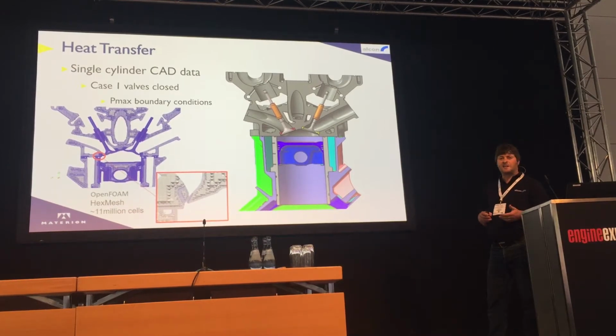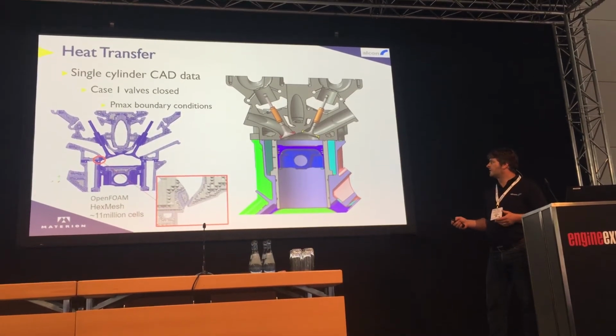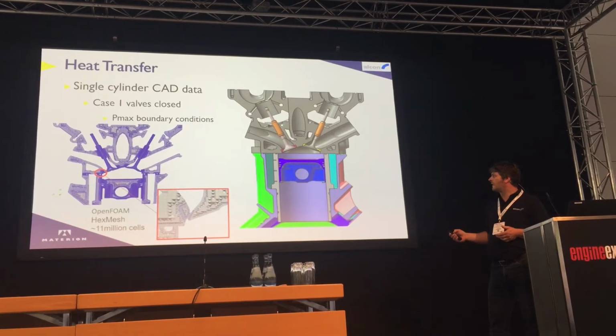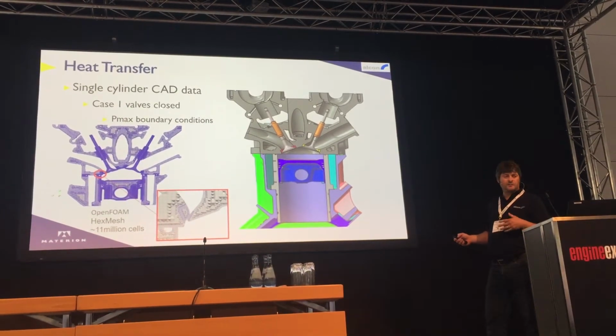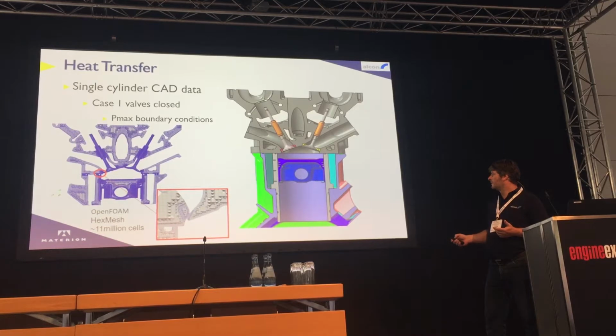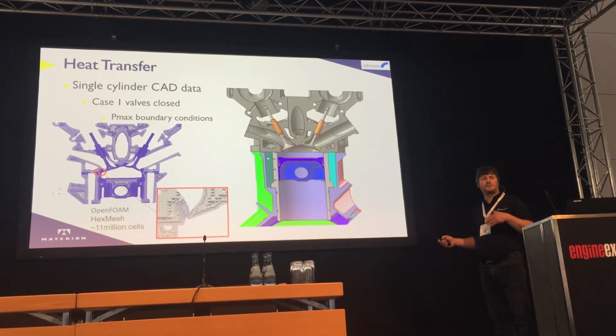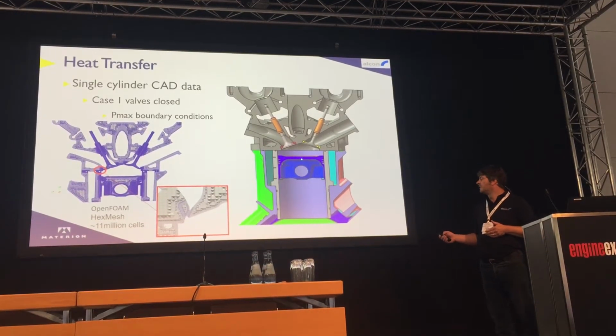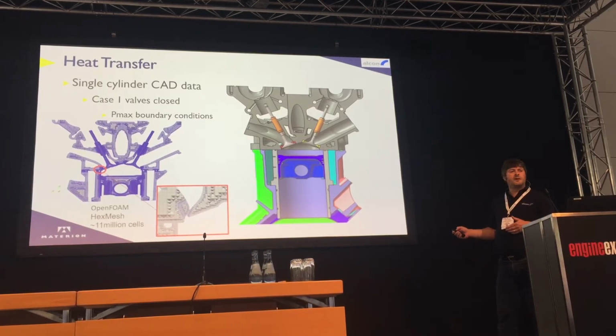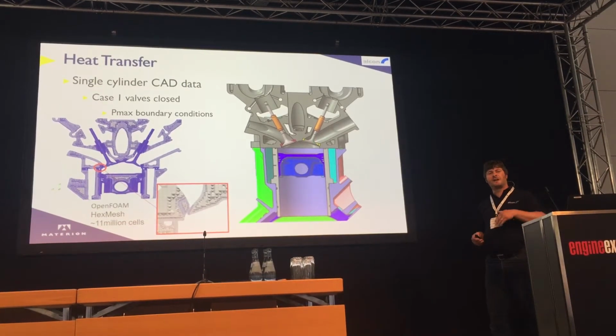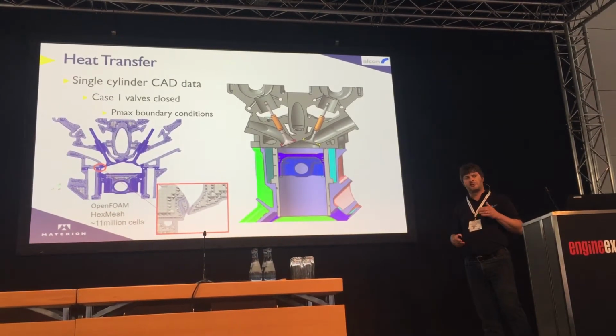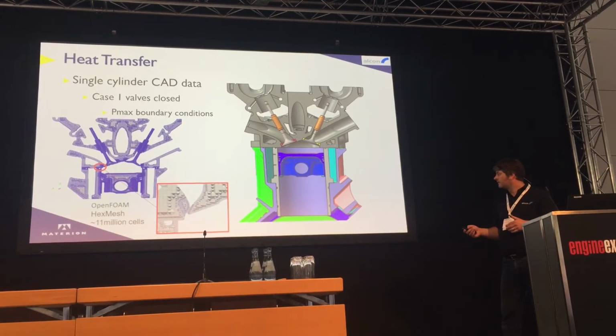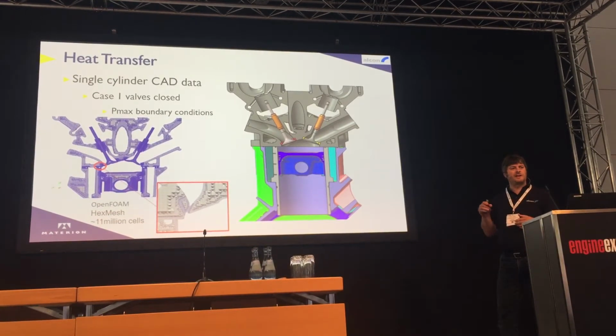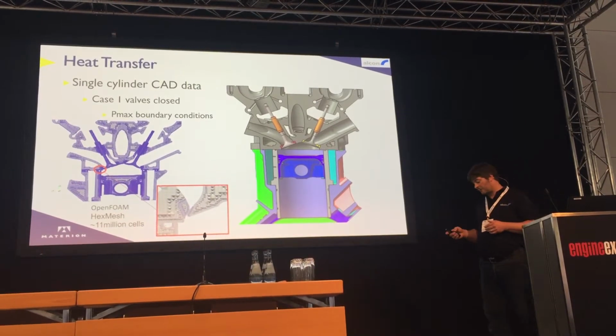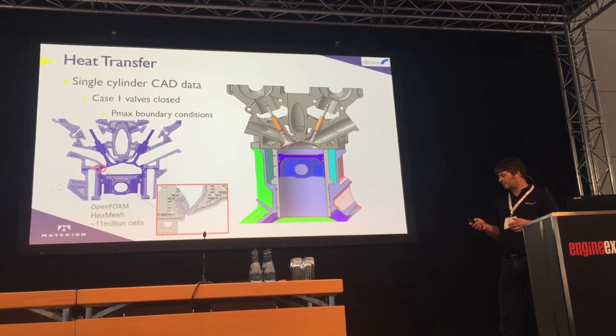It's very much a simple heat transfer analysis. We looked at a couple of different cases. The one I'm showing today is a single case where we're looking at Pmax boundary conditions. So shows the piston in the bore. It's about 15 degrees after top dead centre where Pmax occurs. 135 bar cylinder pressure. This engine's been operating up to about 170 bar. So we actually looked at some different boundary conditions with higher cylinder pressures. And the bottom line was we were looking at the effects on changing the heat transfer, thermal conductivity, and looking at its effect on temperatures.